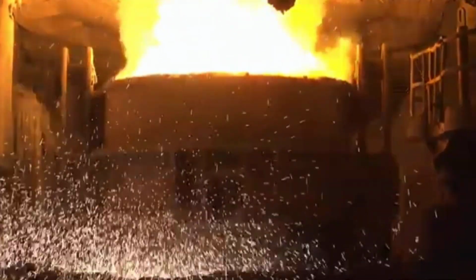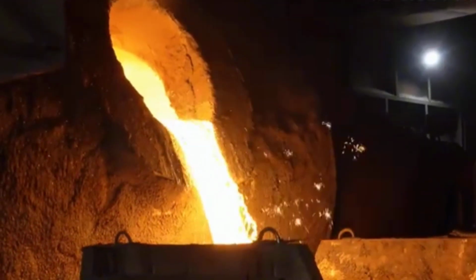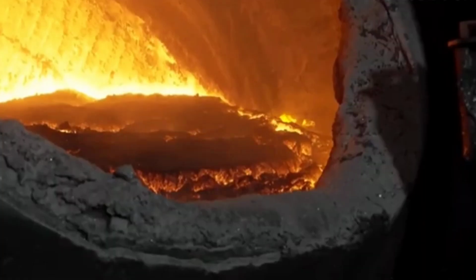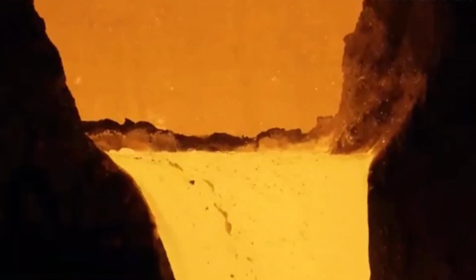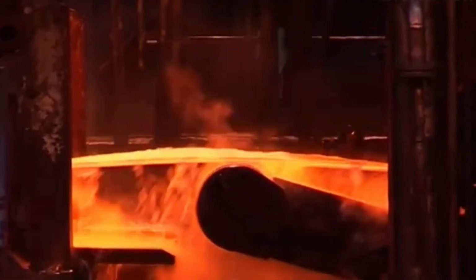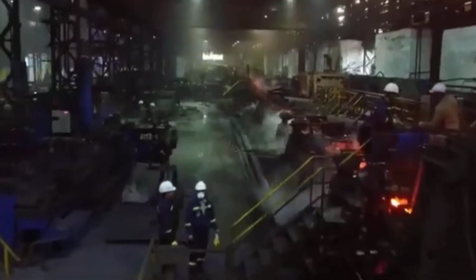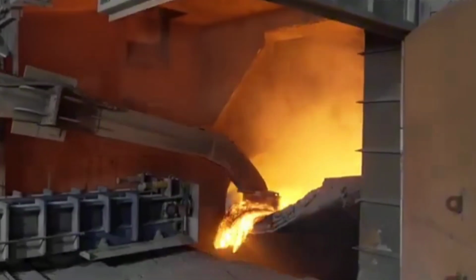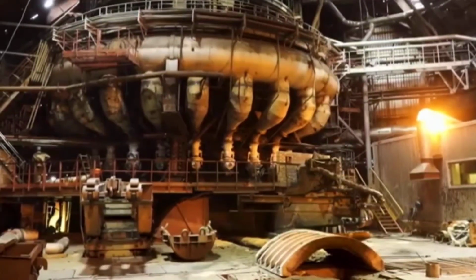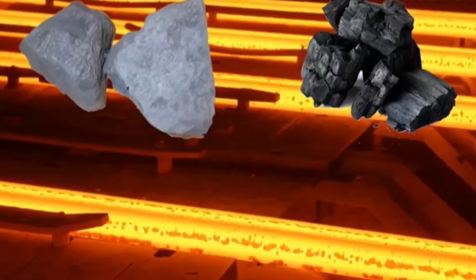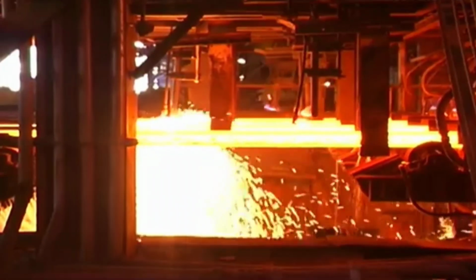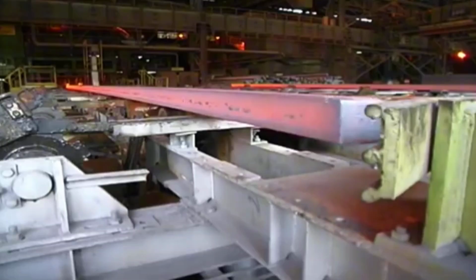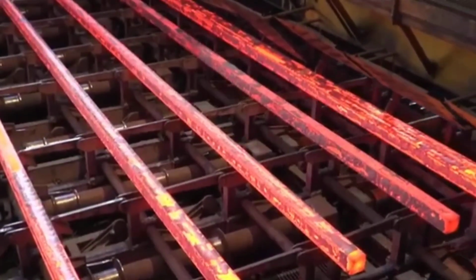To fix this, the molten metal is transferred to a refining furnace, either a basic oxygen converter or an electric arc furnace. In these tightly controlled environments, impurities are carefully removed, while precise amounts of alloying elements are added. Carbon increases hardness, chromium improves corrosion resistance, and additions like molybdenum and vanadium enhance strength, toughness, and wear resistance. The result is high-grade steel with a stable chemical composition and uniform internal structure. It's cast into billets or round bars, ready to be cut, shaped, heat-treated, and ultimately sharpened into a blade. This refined steel is the silent foundation behind every high-performance knife.